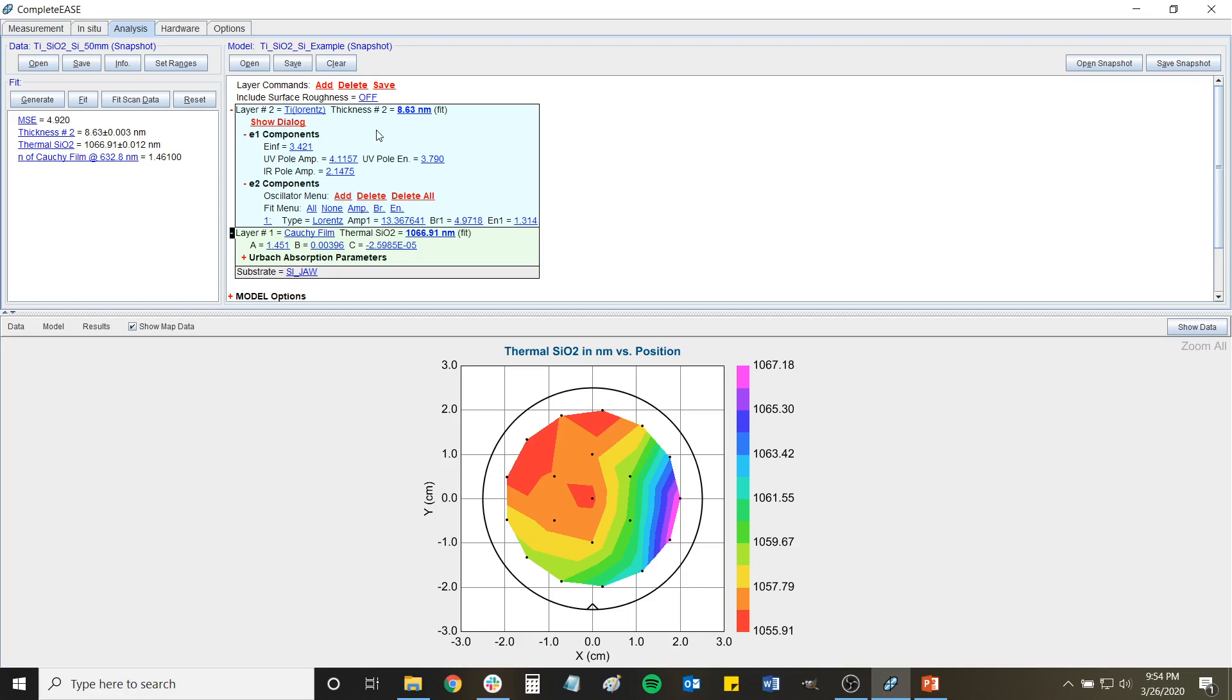And then I built a model for titanium by modeling a very thick film of titanium, deposited it via the exact same parameters and conditions as I did in this situation, except this time I have a much thinner layer such that I can analyze the thickness. So this technique is one that you can use with pretty good accuracy.